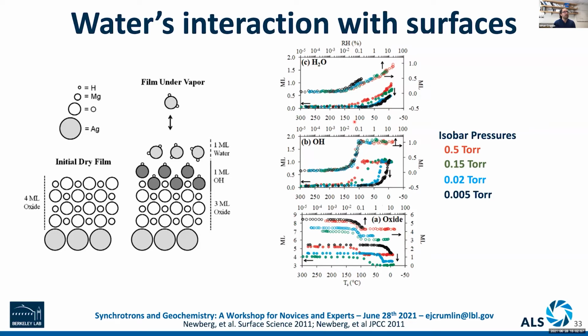And so we can see they're doing isobar pressures as a function of different temperatures. This changes the relative humidity, but they're able to see the transformation of that water to various hydroxides, as well as when you can get some form of water stabilizing in the molecular form on the surface. So the relationship between the hydroxylation and the water formulation, they're able to see in an isotherm and isobar fashion.